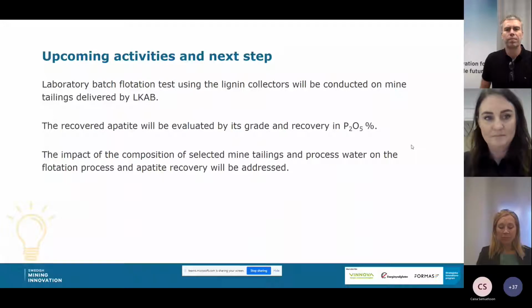Upcoming activities and the next steps: laboratory batch flotation tests using the lignin collector will be conducted on mine tailings delivered by LKAB. The recovered apatite will be evaluated by its grade and recovery, and the impact of composition of selected mine tailings and processed water on the flotation process and apatite recovery will be addressed.